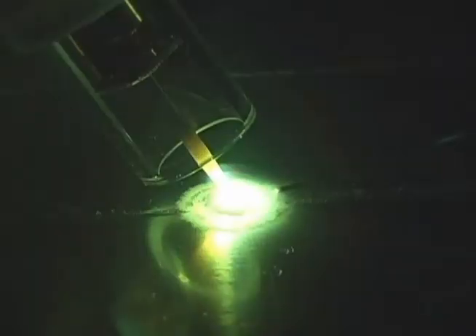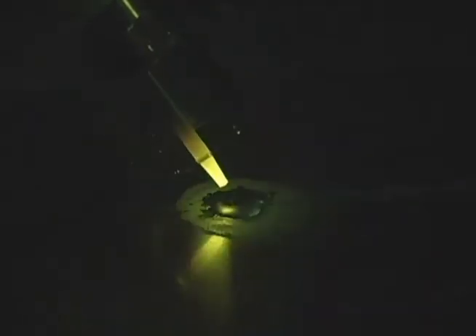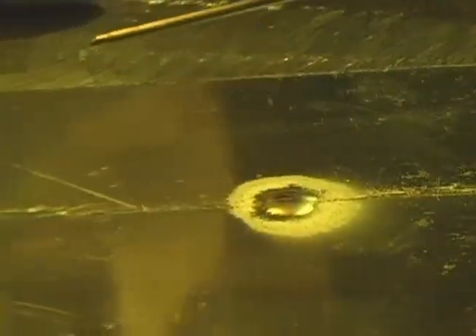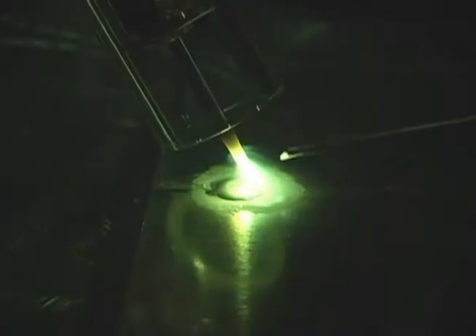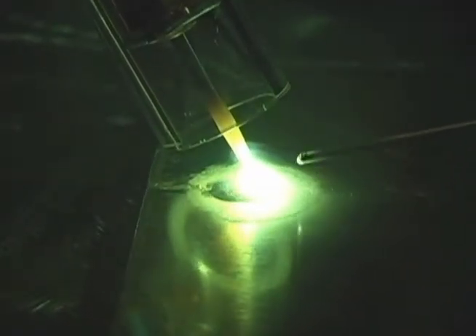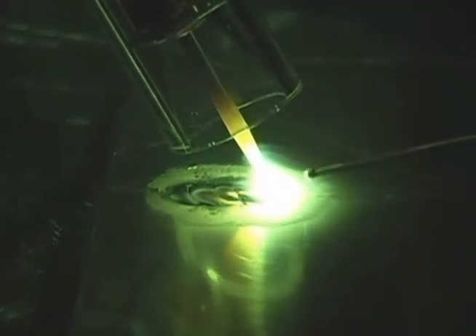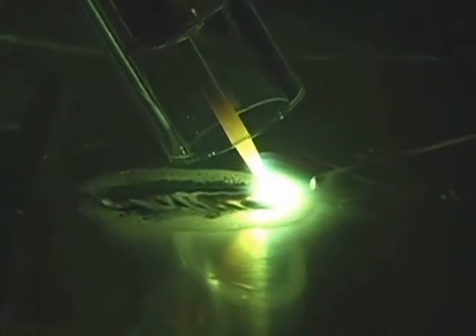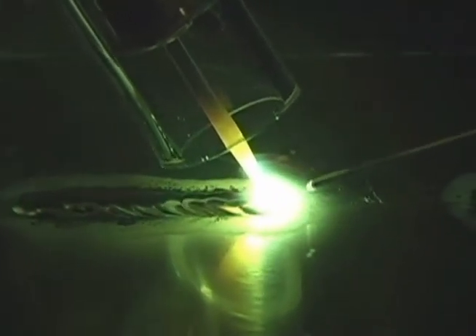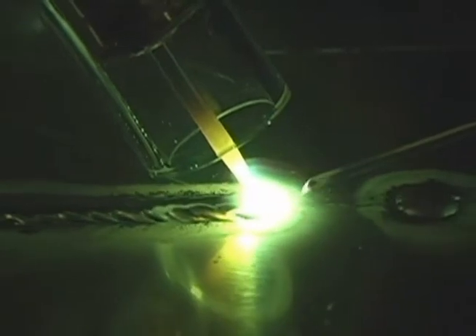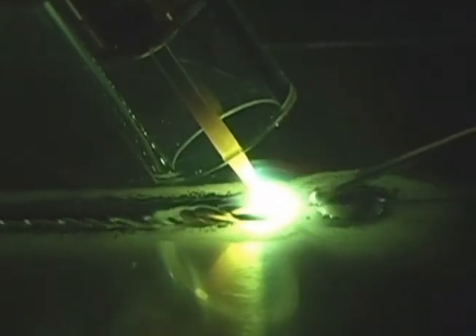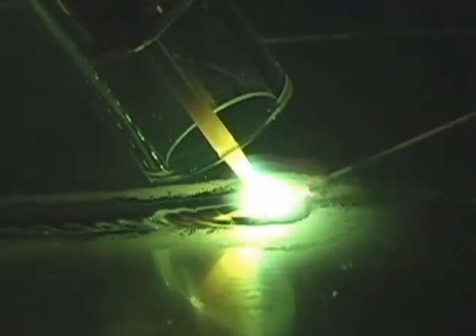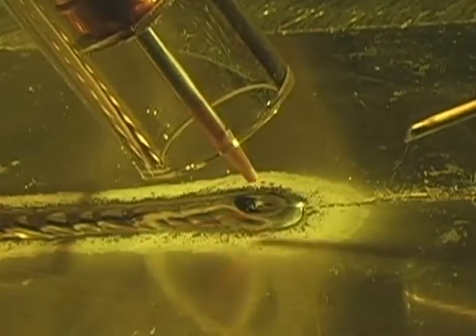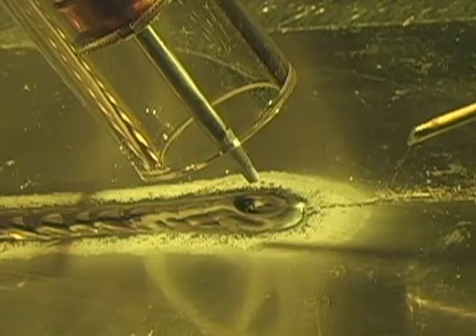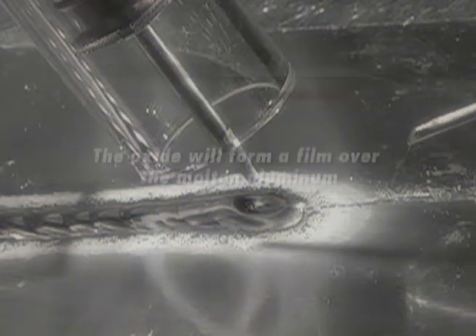Aluminum has some unique characteristics which differ from steel. Aluminum does not change color when it is hot or molten. The only way you can tell when aluminum is molten is the puddle becomes shiny. Aluminum forms an oxide as soon as it is exposed to the atmosphere. The problem with the oxide is it melts at 3200 degrees Fahrenheit, much higher than the melting point of pure aluminum, which is approximately 1100 degrees Fahrenheit.